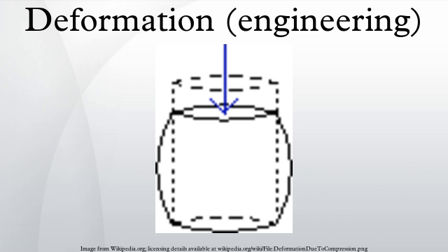Metal fatigue has been a major cause of aircraft failure, such as the de Havilland Comet accidents, especially before the process was well understood. There are two ways to determine when a part is in danger of metal fatigue. Either predict when failure will occur due to the material, shape, and iteration combination, and replace the vulnerable materials before this occurs, or perform inspections to detect the microscopic cracks and perform replacement once they occur. Selection of materials not likely to suffer from metal fatigue during the life of the product is the best solution, but not always possible. Avoiding shapes with sharp corners limits metal fatigue by reducing stress concentrations, but does not eliminate it.